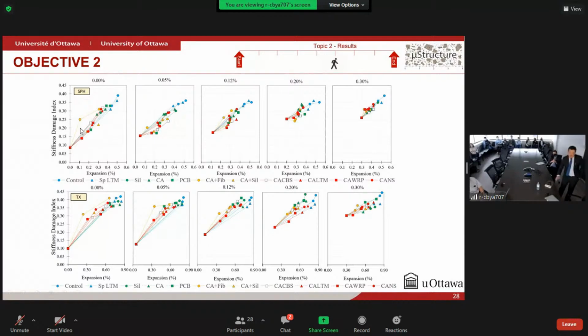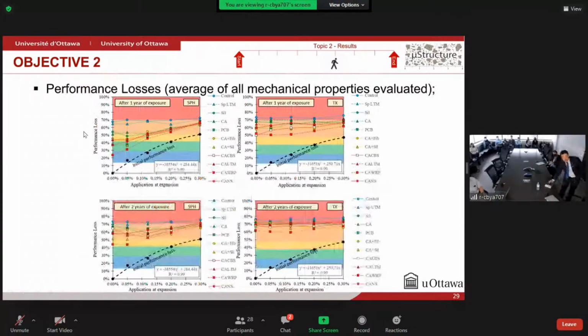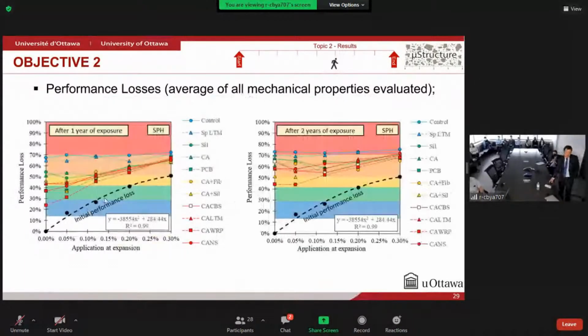At the end of this objective 2, we propose different charts in which we correlate the performance loss of the concrete specimens with the different surface treatments. I would like to emphasize here that the performance loss was calculated as the average of all mechanical properties evaluated in this research. So just zooming in here to explain the charts. At the bottom of the charts here, we have this black dashed line that represents the initial performance loss of the concrete before the application of the different surface treatments.